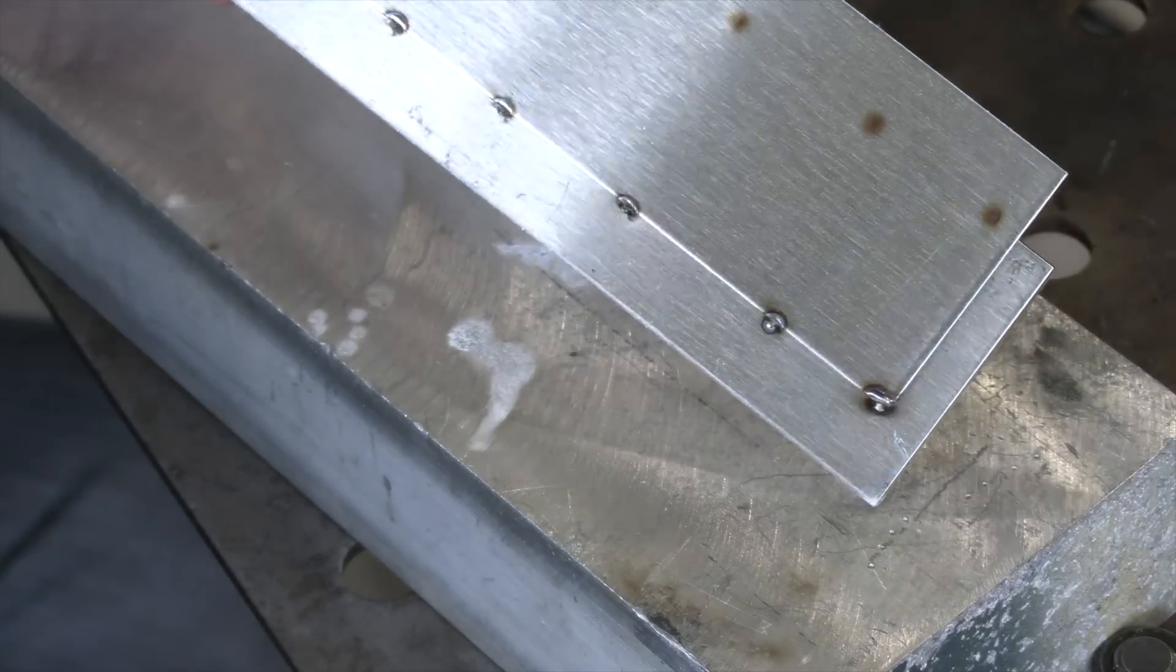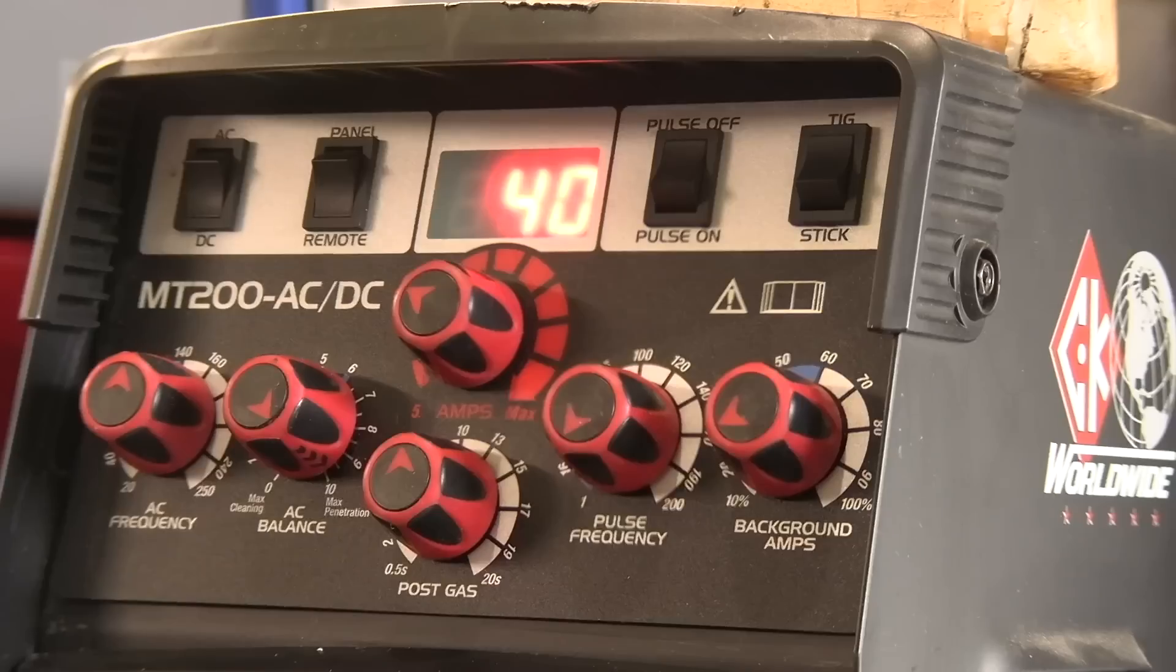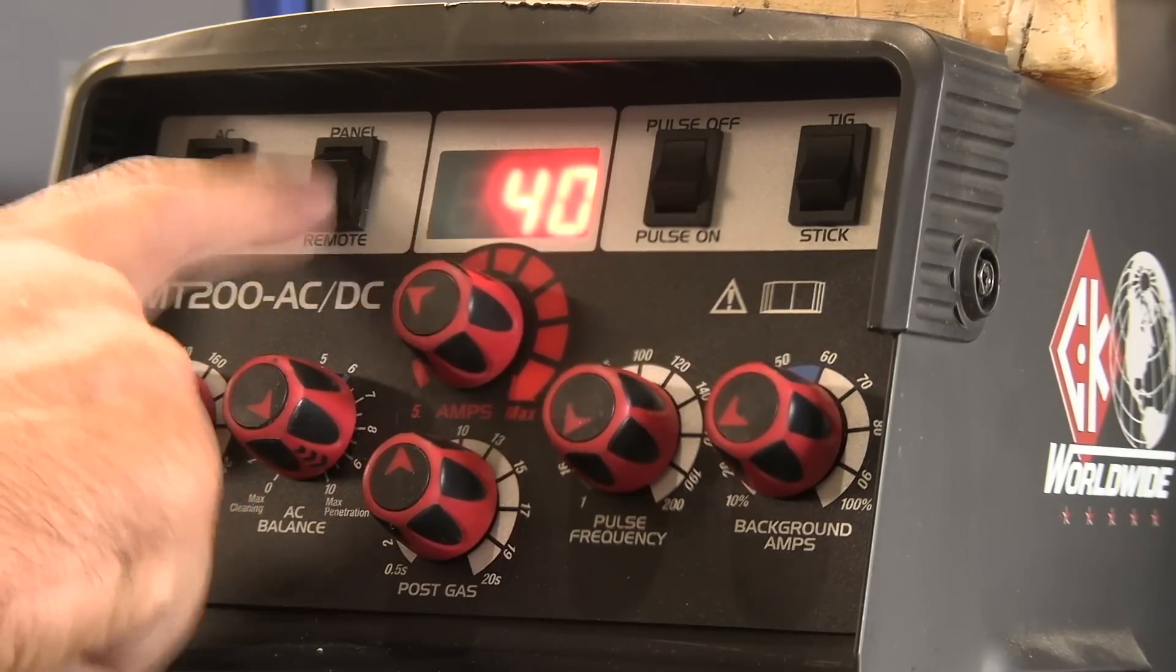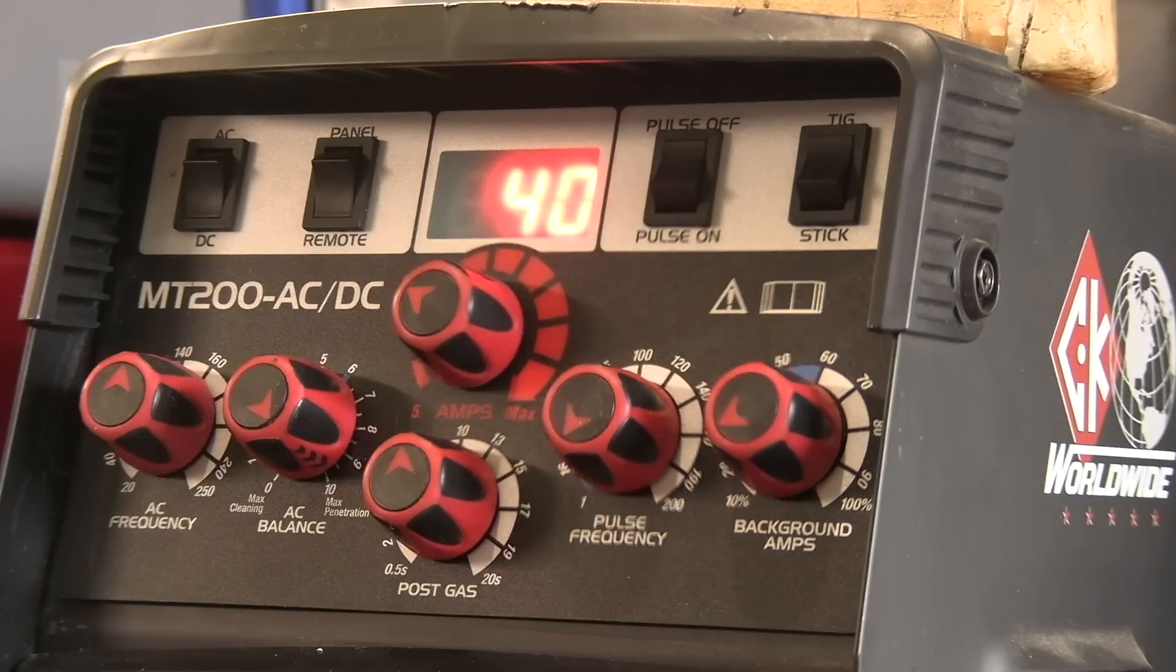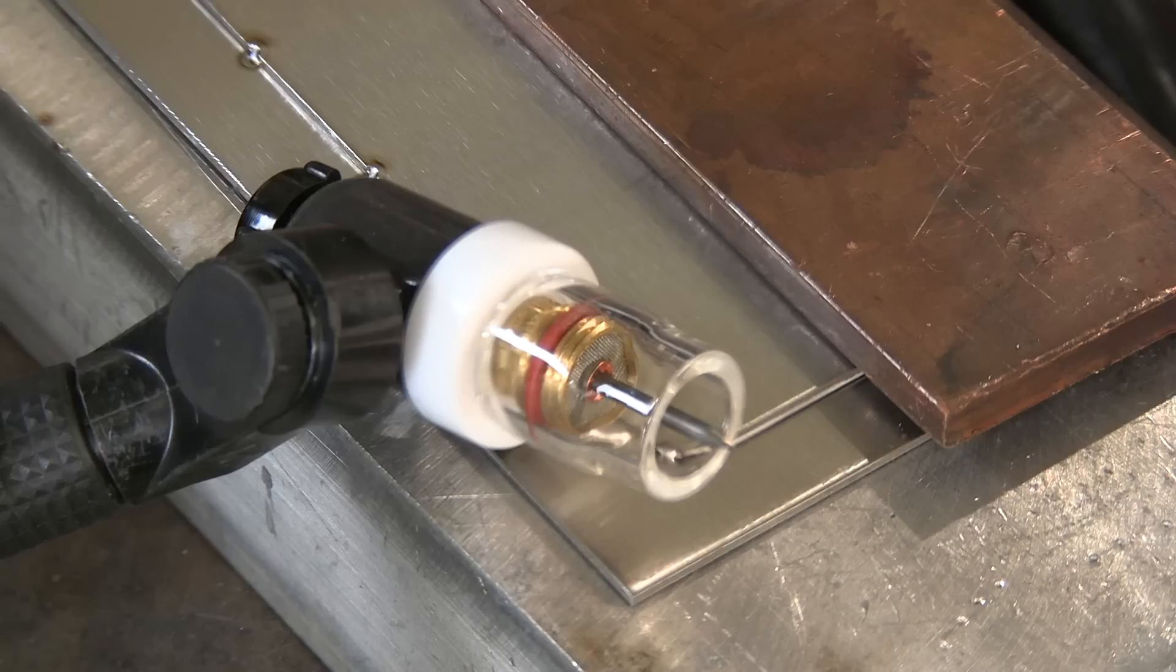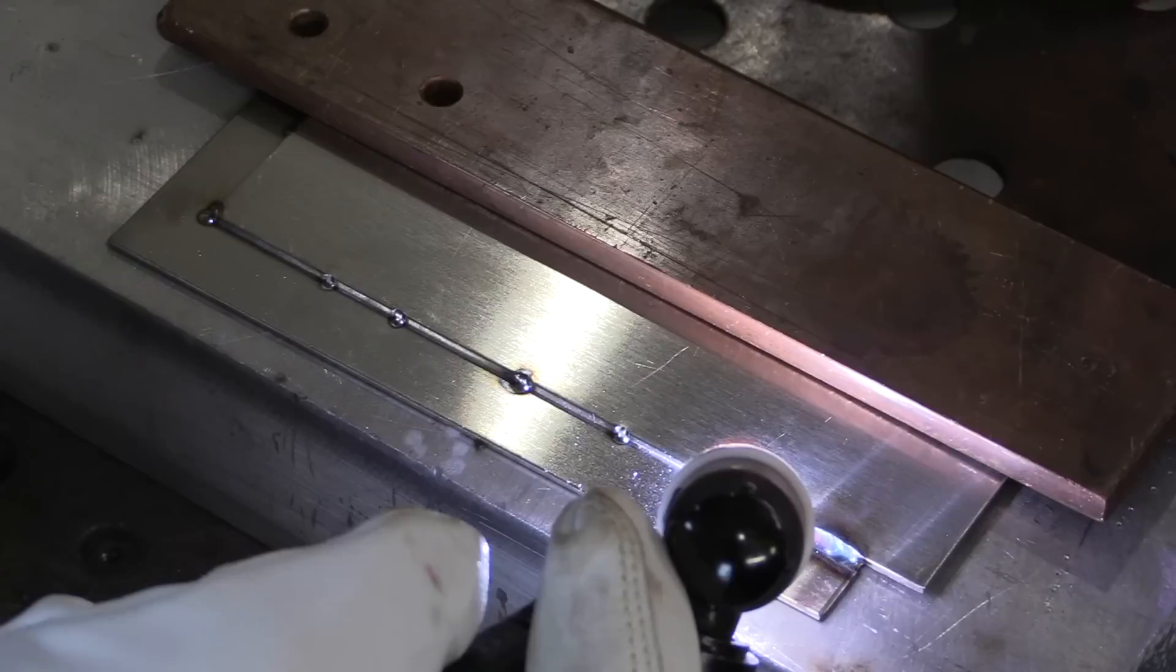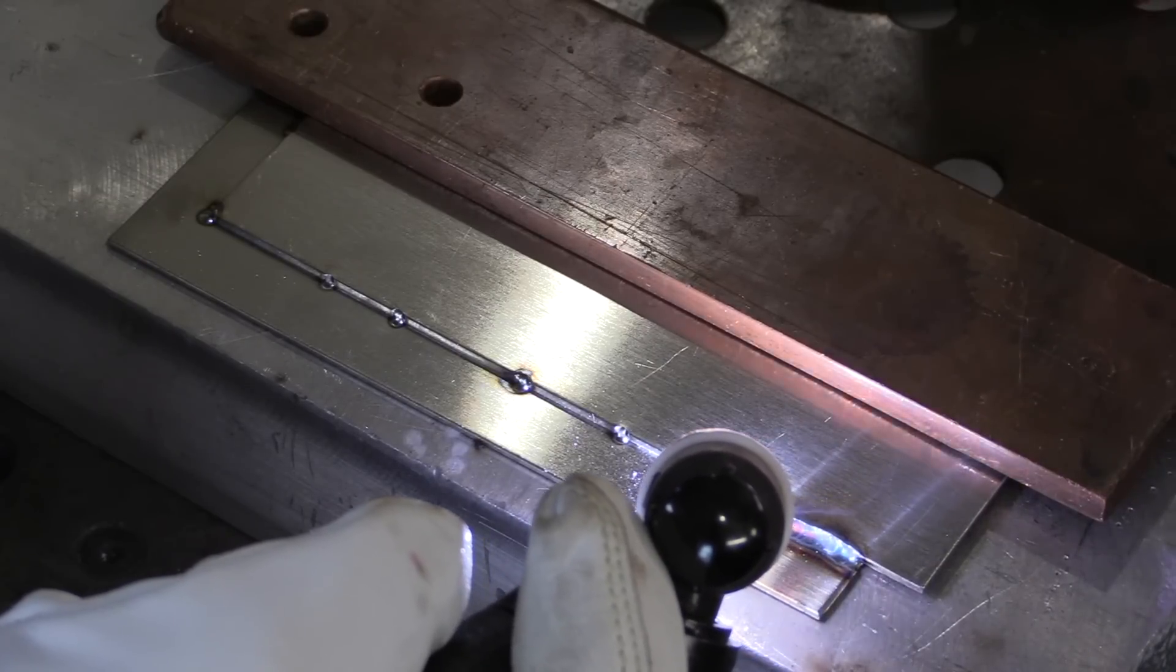Now let's weld it out. We're going to start off with 40 amps. You got to remember to turn the switch back on remote, or you'll have 40 amps as soon as you hit the pedal. I'm going to change over now to a number eight pro clear cup, and so I'm going to go ahead and increase the argon flow rate up to about 20 to 25. This is an example of a 16 gauge autogenous lap joint, 40 amps.